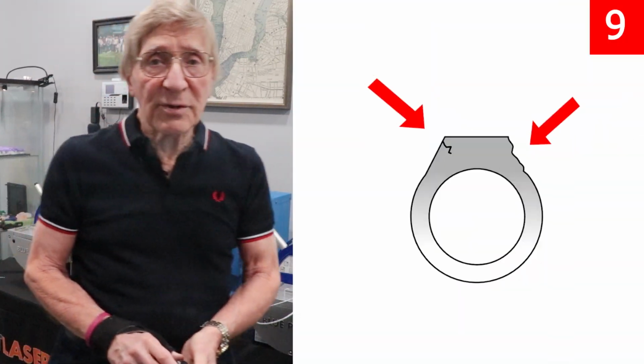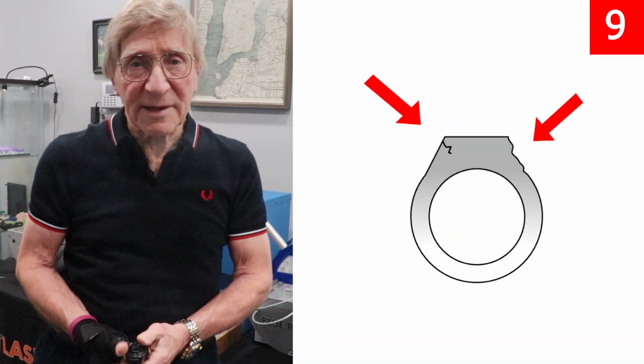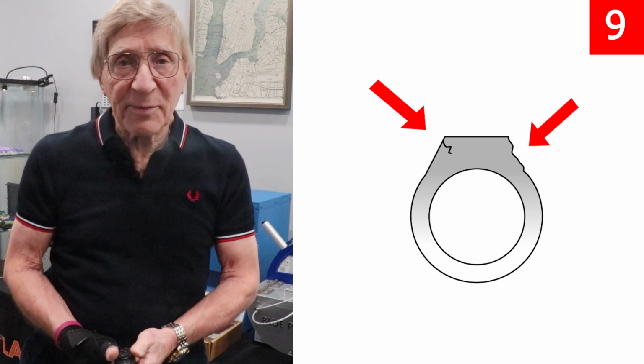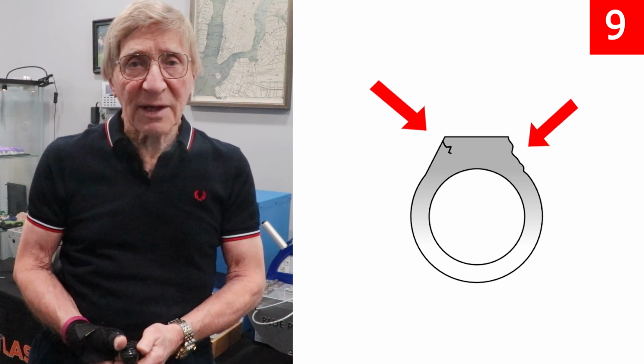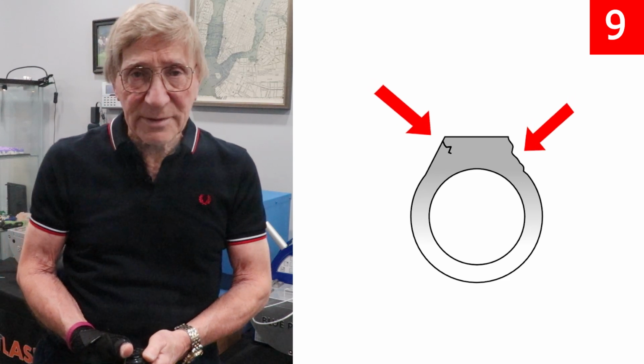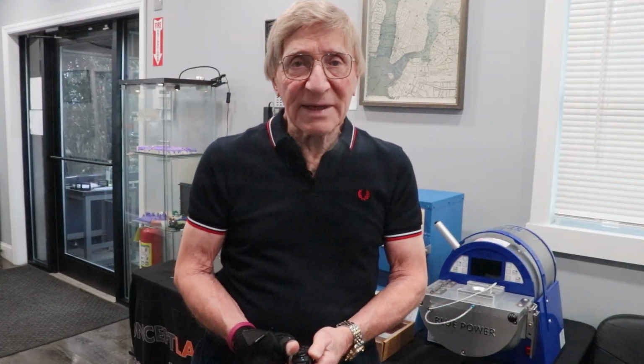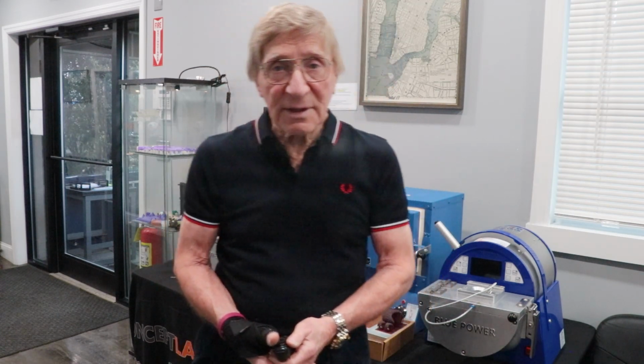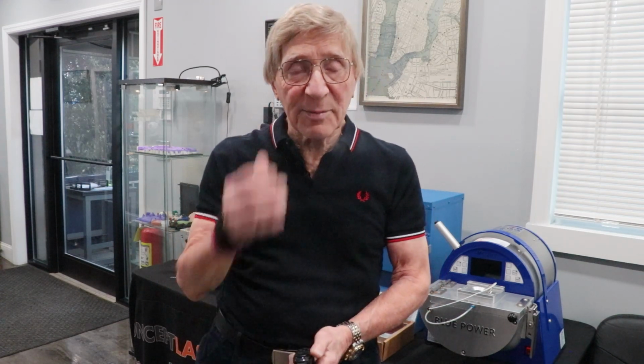Diagram 9 could be the result of an improper burnout cycle. The problem can be that this operator has allowed the temperature in the oven to climb too rapidly during the first hour, so that the wax, instead of melting out smoothly and easily from the tree, has boiled in the cavity and broken down the surface of the investment to which it was immediately adjacent. The result is the rough surface that you see. Also, it will happen if the waxes are not placed at a 45-degree angle on the tree for easy drain out of the wax.